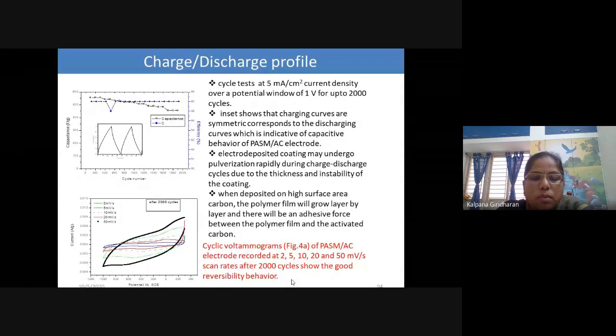This is a cyclic voltammogram for different scan rates. The discussion is, when you deposit a high surface area carbon, the polymer film will grow layer by layer, and there will be an adhesive force between the polymer film and the activated carbon.